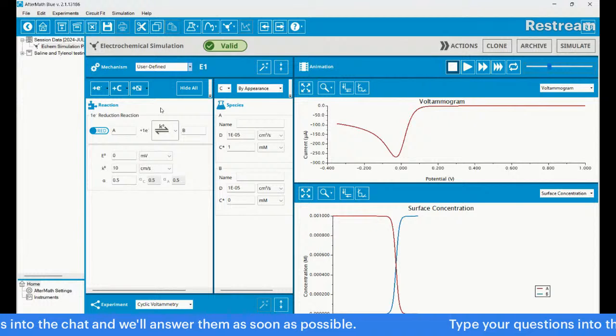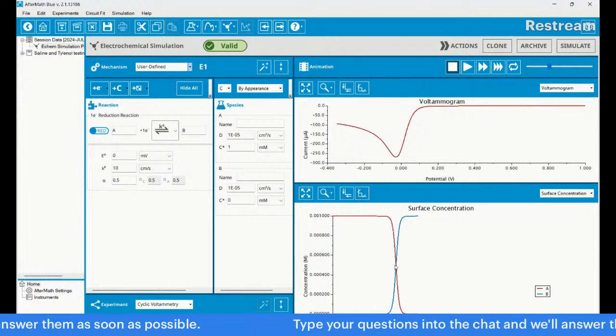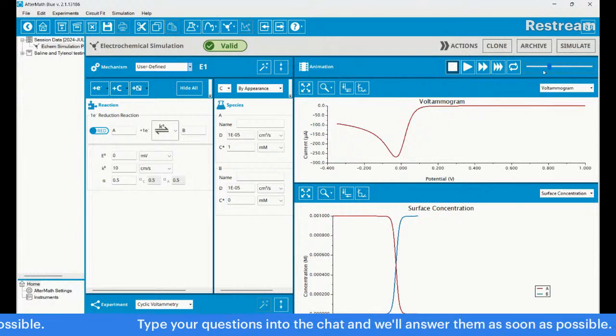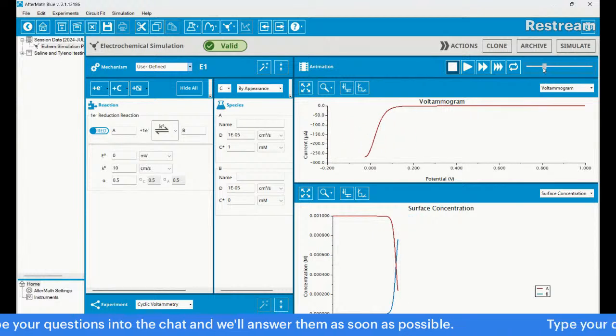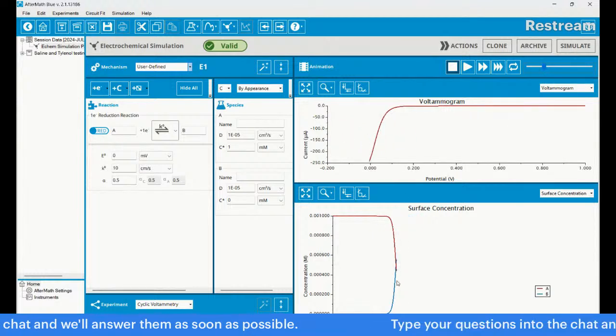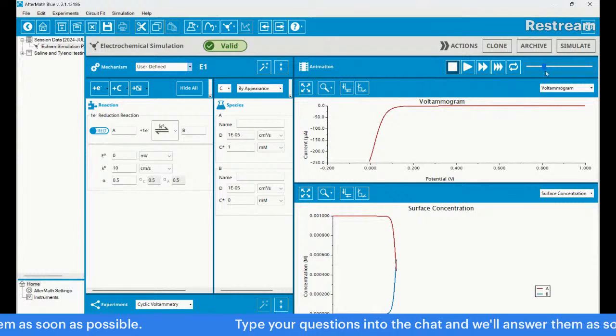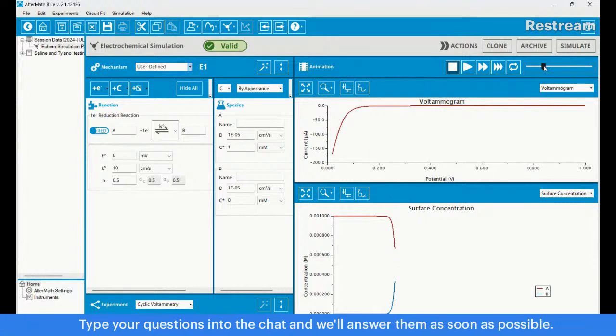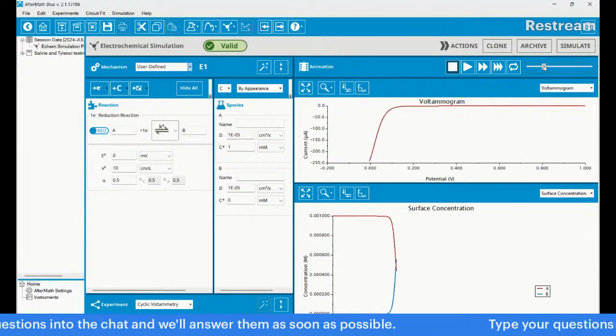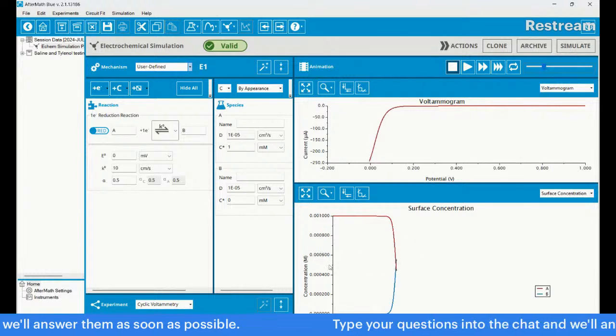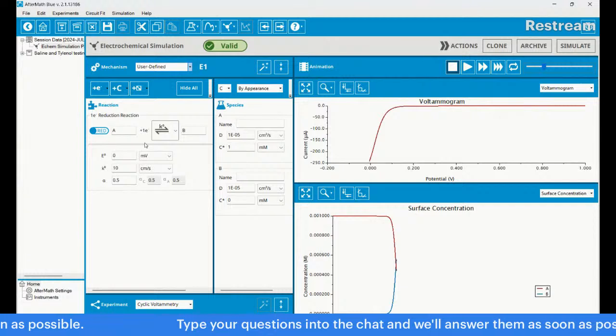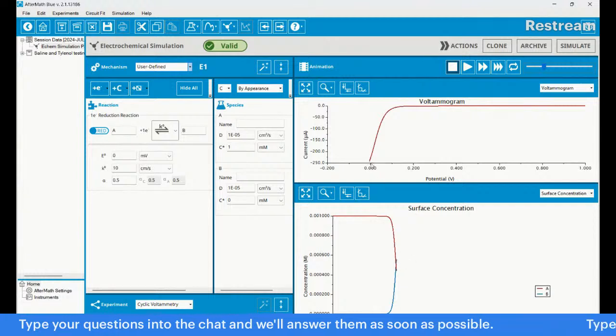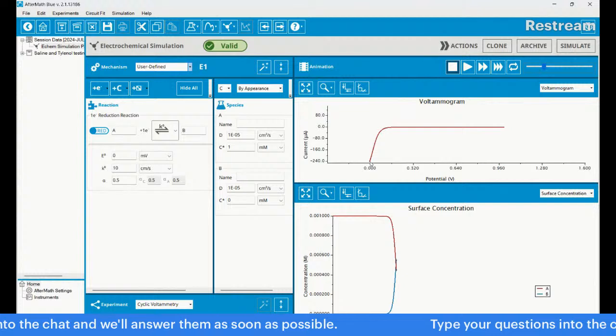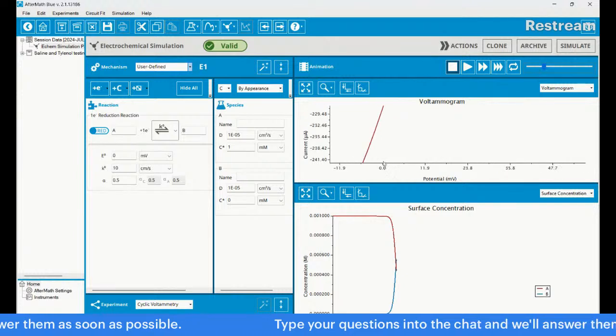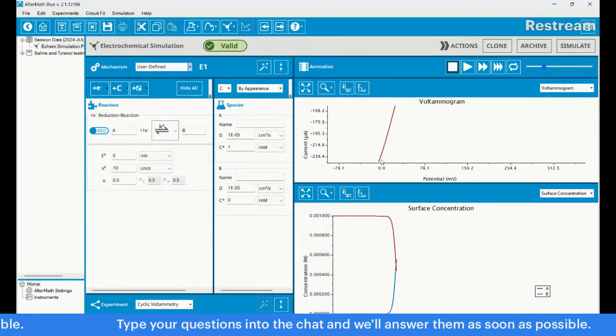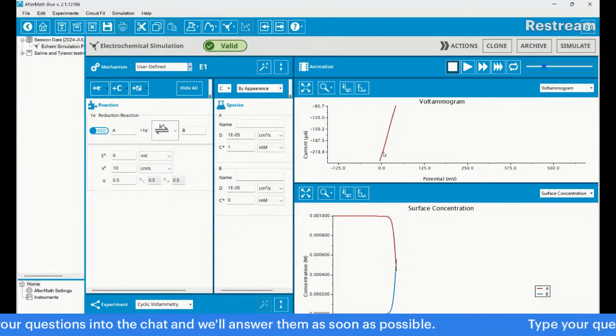And more specifically, it represents the point where the concentration profile, so during our voltammogram, you have two things. You have species A and species B. But the point where their concentrations actually intersect, so I'm going to try to very carefully get to basically the midpoint. Right when it's at this midpoint here, when the concentrations are equal, and I don't think I can iterate just enough, but pretend that these two are exactly the same. When the concentration of A and B are 50-50, that actually aligns with 0 here. It's a little bit hard to see because I've gone just past it, but when this is 0, when the concentration is 50-50,